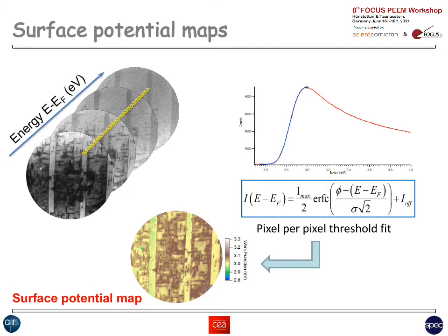And as you can see, there are three basic levels of intensity: bright yellow, dark yellow, and brown, and these correspond to three distinct surface potential values, reflecting the three possible polarization orientations at the surface of barium titanate: out of plane pointing upwards, out of plane pointing inwards, and in plane. So we have a true surface potential map reflecting the ferroelectric polarization.